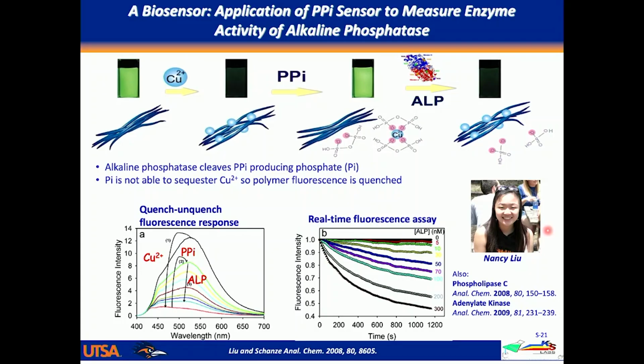And you can see that experiment here in real time. This is representing the fluorescence of the polymer in the green region, and these are different amounts of the alkaline phosphatase added, 5, 10, 20, 50 nanomolar, and so on. And you can see over time of about 10 minutes, the fluorescence is going down. And that decrease in fluorescence is due to the quenching of the fluorescence of the polymer due to the copper going back onto it. And basically it's transducing the hydrolysis reaction of the pyrophosphate by the alkaline phosphatase enzyme.